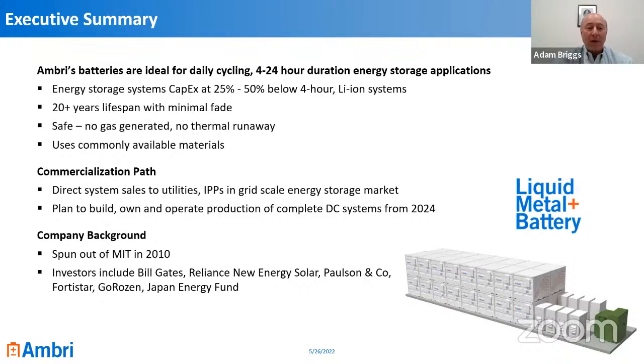Part of the reason the economics are so attractive is because it does not have any meaningful degradation. It has a 20-year lifetime with a maximum 5% degradation over those 20 years with everyday usage during those 20 years. So that translates into 7,300 cycles. The battery system does not exhibit any degradation in capacity due to usage. So it could be 2 cycles per day, 3 cycles per day, not really a problem.